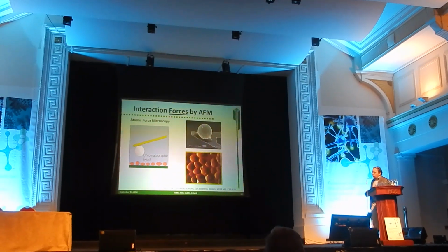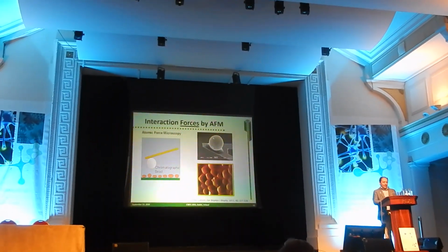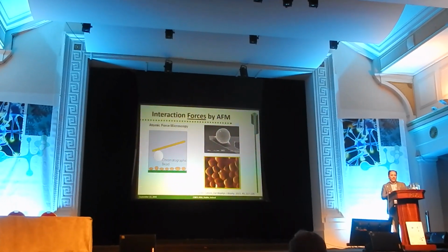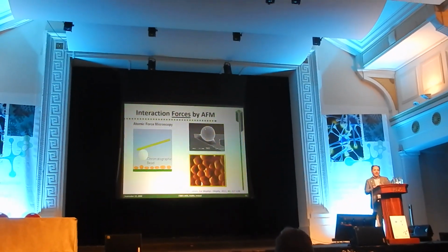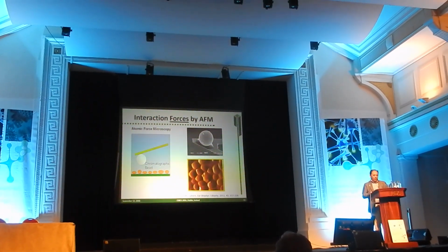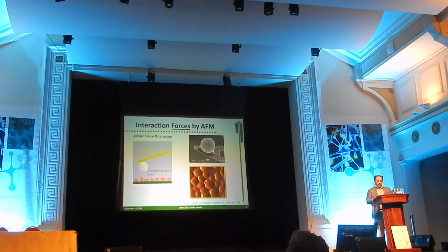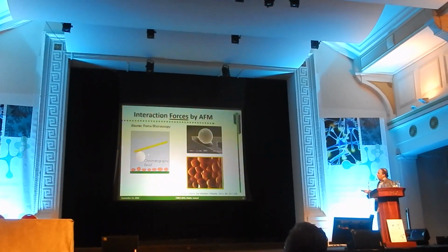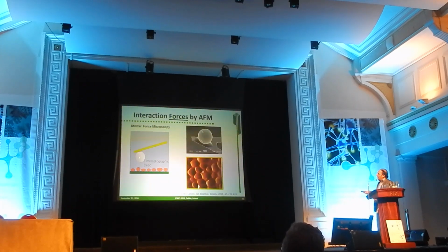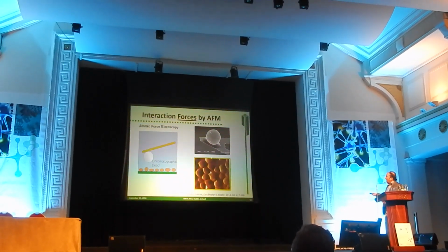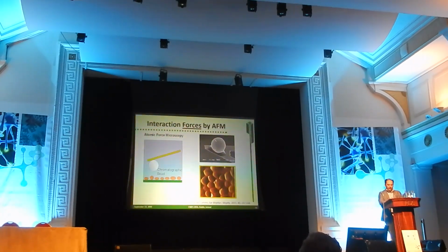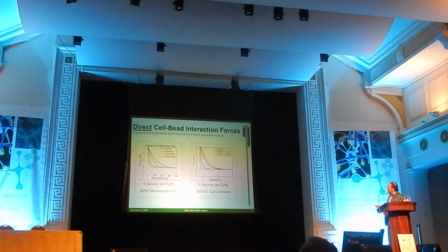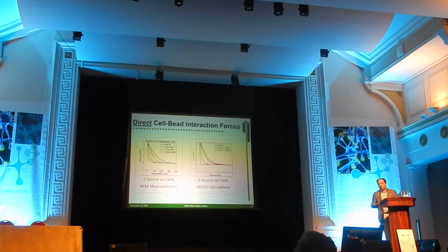Okay, another question, a little bit more basic, was: are these energies really meaningful? How can we access these forces in a different way? A different way would be to determine direct contact forces, right? And this we can do with atomic force microscopy, and this we did. So we basically glued the chromatographic bead on the AFM cantilever, here on the top, and we expose this modified cantilever to the cells deposited on the surface, and we got, this is just one example,